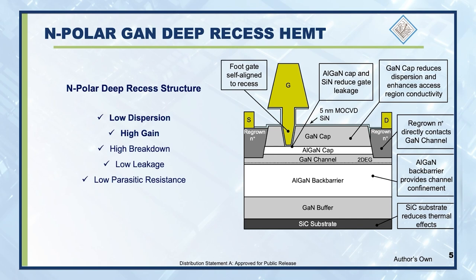There's an aluminum gallium nitride back barrier. This aluminum gallium nitride back barrier, on which the gallium nitride is grown, provides the back barrier for channel confinement, and you also have the two-dimensional electron gas induced at the GaN-AlGaN interface. And then you have,